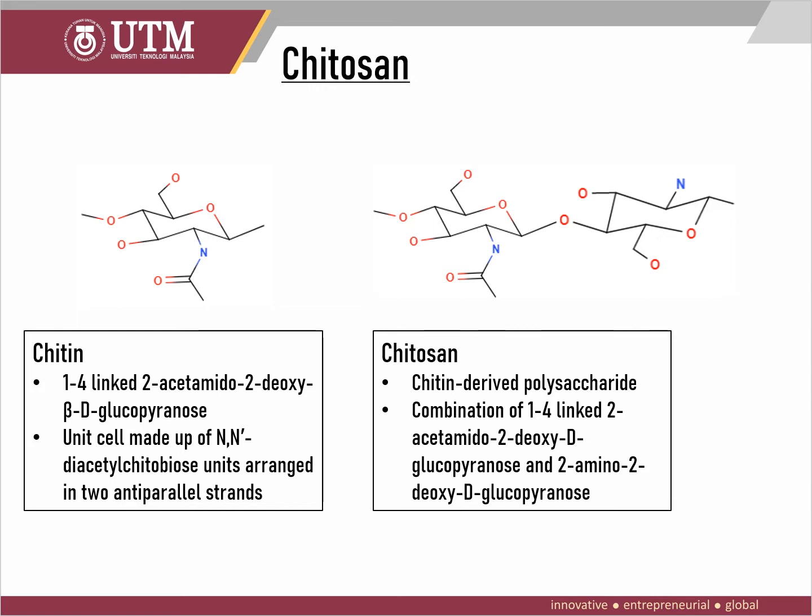As a result, adjacent polymer chains are kept together by C6-HO6 hydrogen bonds, while the chains are maintained in sheets by C7-HN hydrogen bonds. Chitosan is distinguished from chitin by the presence of amino groups, which is reflected in its solubility in dilute acid, pH below 6, as well as its ability to form complexes with metal ions, allowing it to be used for wastewater treatment and purification. Chitin, on the other hand, has very few practical applications due to its low solubility, if any.